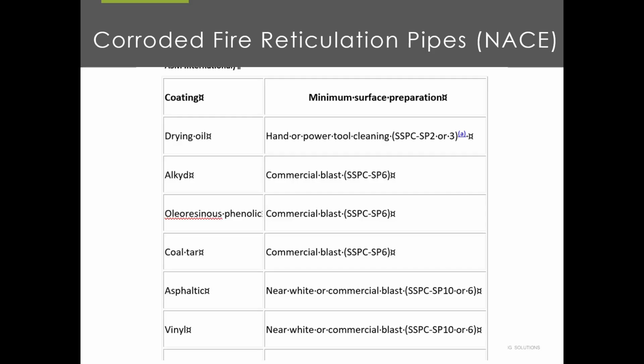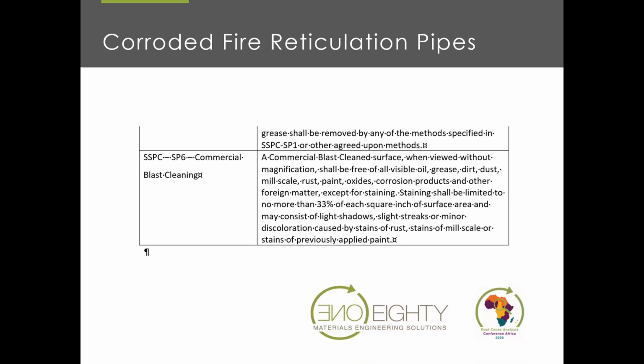Okay, so here's a description. A commercial blast clean surface when viewed without magnification shall be free of all visible oil, grease, dust, mill scale, paint, oxides, corrosion products, and so on. So that is the description of the SP6, which goes with the alkyd paint system. But clearly from the electron microscope images, that was not the case.